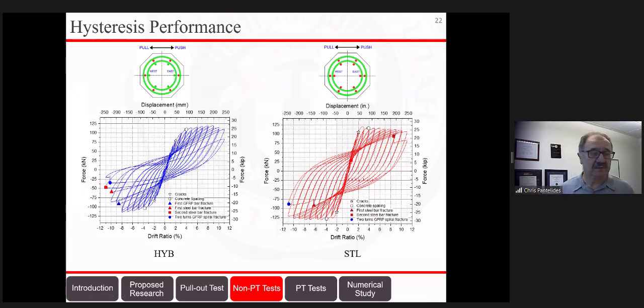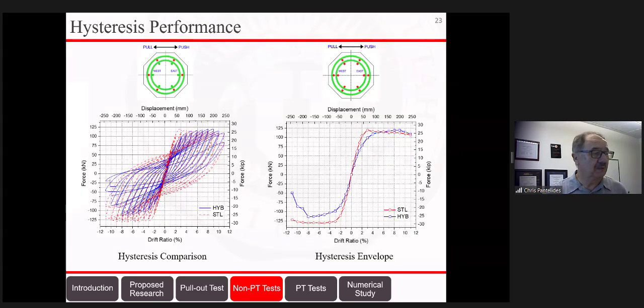This may seem to be a common conclusion, but the reality is that there are new things here where, for example, we're using fiberglass spirals and 2 layers of it. So this is really a new result. It hasn't been shown in the literature. But I would say that if we compare the performance of these two, which is shown here, again, the hybrid is in blue and the red is in steel, you can see that the hybrid achieved good capacity, 120 kilonewton at 9% drift ratio. The steel column achieved a little higher, 130 kilonewton, and that was achieved earlier at 6% drift ratio.